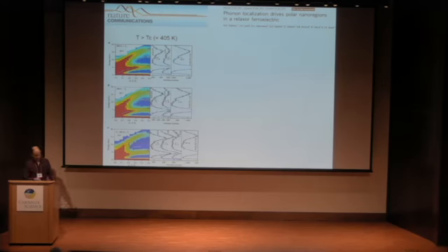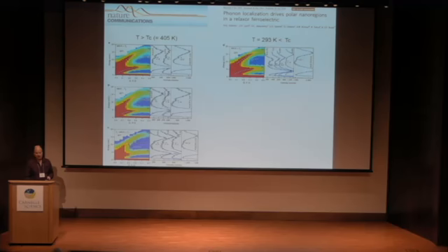He has already discussed the fact that he sees a local mode, these little peaks here, that seem to indicate a dispersionless excitation at high temperatures above Tc, which is roughly 400 Kelvin, but that when you cool down below Tc, in this case around room temperature, it develops a dispersion, so it delocalizes. That was the essence of this paper.